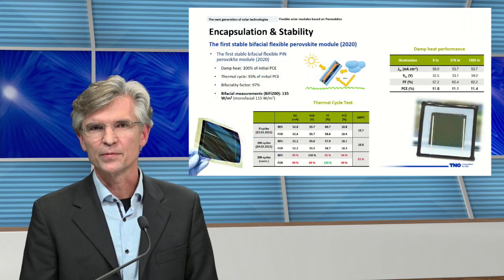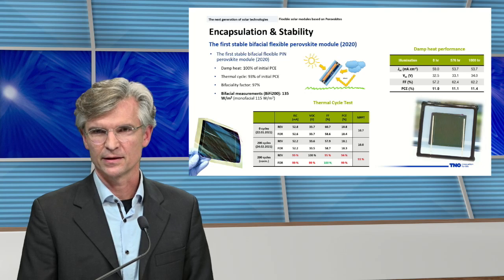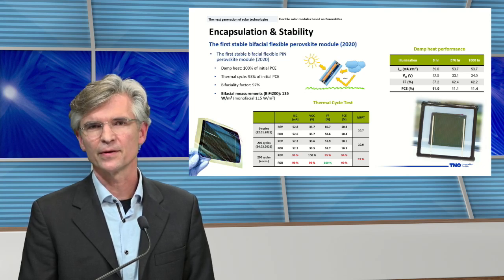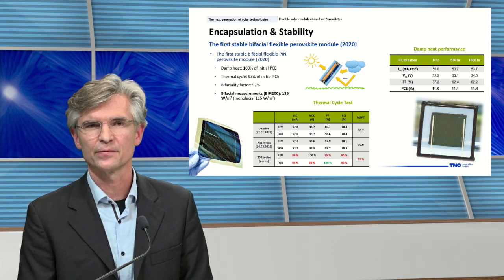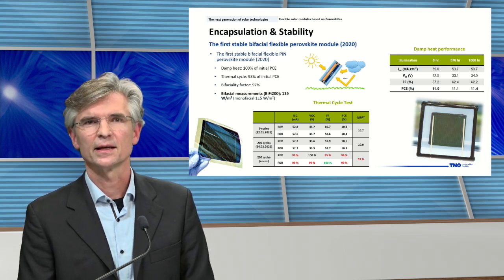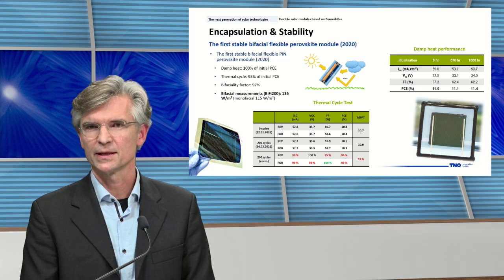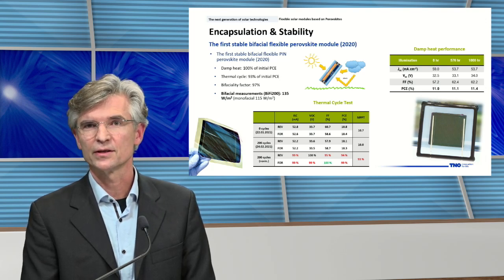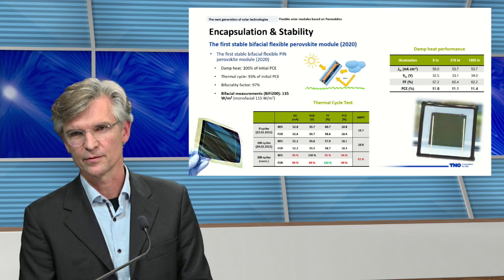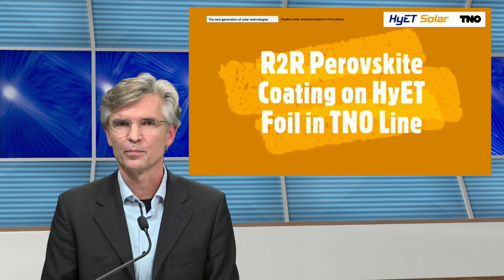Here we see that we can obtain this stability also on bifacial devices that have a high bifaciality factor of 97%. They can pass thermal cycling, damp heat test, and achieve a power conversion efficiency of 11%. Now we can have a look at a video where we process perovskite on a roll-to-roll line.